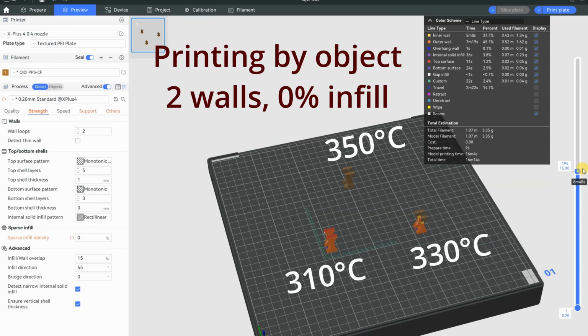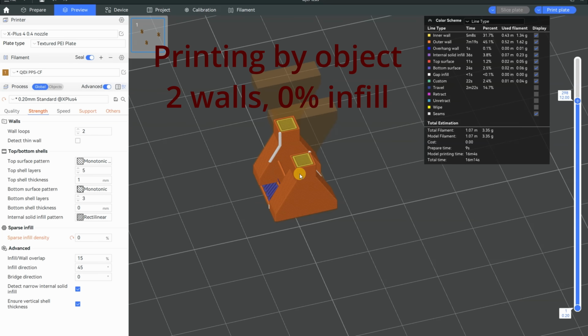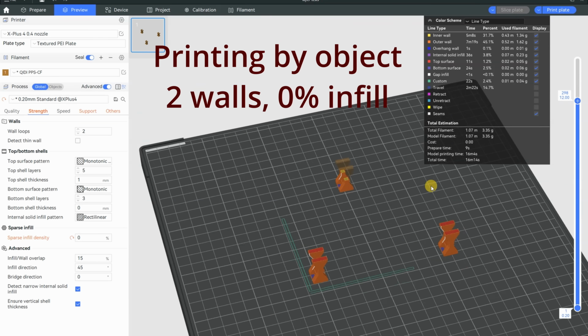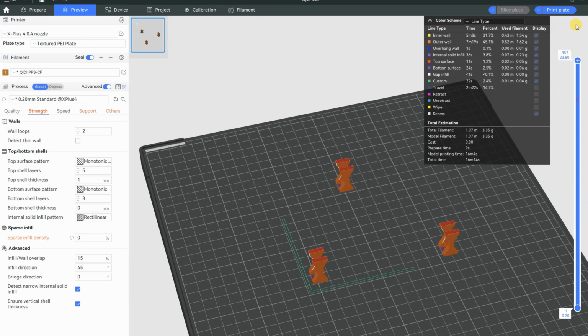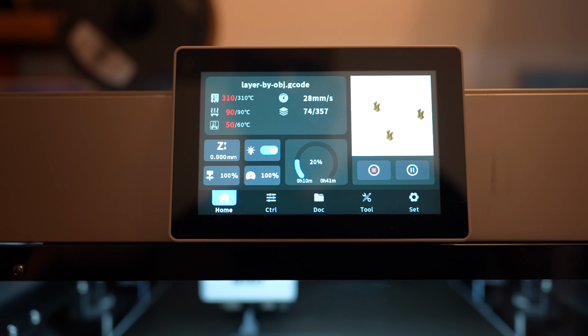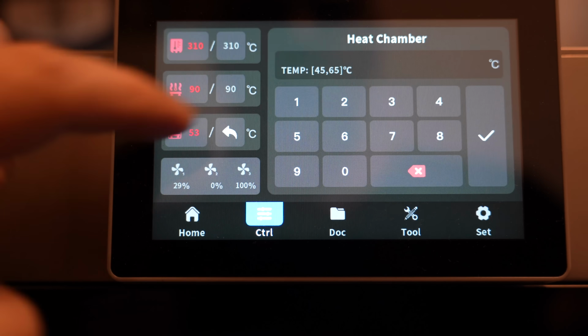To decide what temperature to use, I'm printing quick layer adhesion tests at 3 different temperatures, objects printed with 2 walls and 0% infill. Here you can see the current settings, and I'm not even sure that I need a 60 degrees Celsius chamber temperature, but this was preset for the QDI PPS, which was in the slicer. I think 50 should be enough.